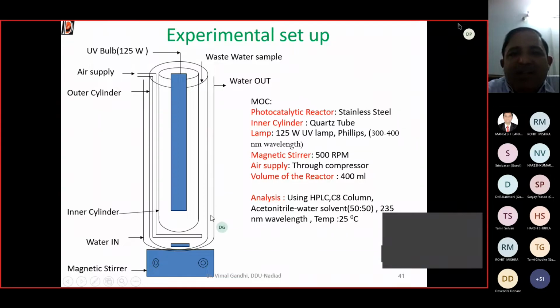The targeted compound was mainly phthalic acid along with some other aromatic carboxylic acids. We monitored operating parameters like calcination temperature, dose, concentration, kinetic study, and degradation of various aromatic carboxylic acids. If you see here, for the effect of calcination temperature, we take two samples, calcined at 400 degrees centigrade and 550 degrees centigrade. And you see here their activity. The sample calcined at 400 degrees centigrade degrades greater than 90% of phthalic acid, with an initial concentration of 100 milligram per liter, 100 ppm, in just less than 2 hours.